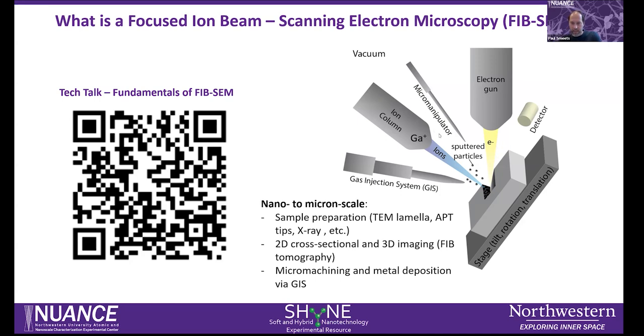There is also frequently a micromanipulator present. If you create a very small section of your material, you can lift that out with a micromanipulator, and move it to the TEM if you thin it down appropriately, to look at your material in the TEM.